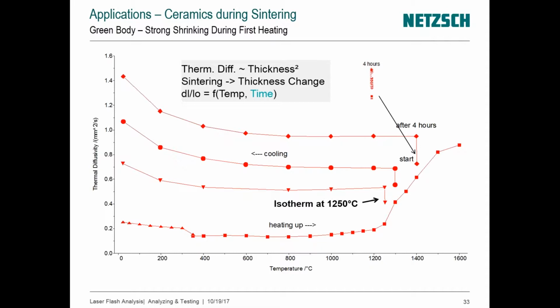And the reason why you see that effect here is more pronounced than what I presented before is simply because the sintering is occurring and we are accounting for it. Essentially, the specimen thickness is decreasing, sintering is occurring, more tighter bonds between the particles, and diffusivity is increasing significantly. And that's exactly what we are showing here with the red curve. Now, we are taking different cases where we would bring the specimen to a given temperature, remain fixed isothermal over a certain period of time, 4 hours, at an isotherm. Let's say in the first case, the triangle marks, we will keep the temperature at 1250 degrees, we will go there, stay there, and then measure on the cooling side.